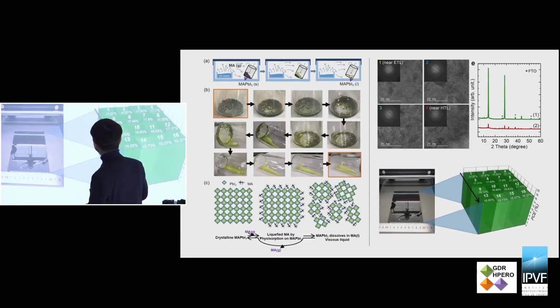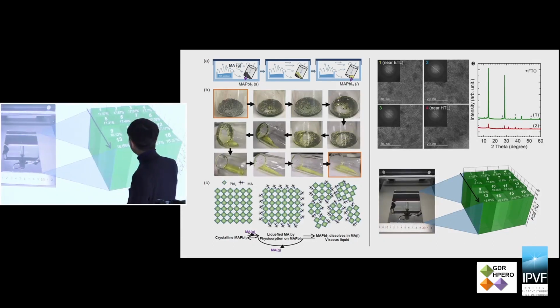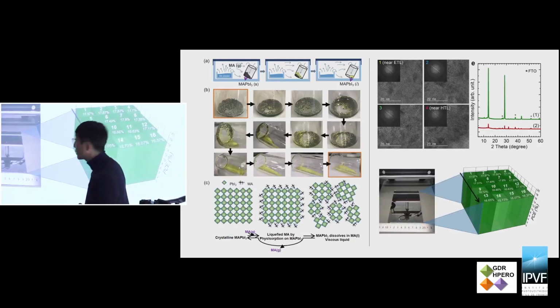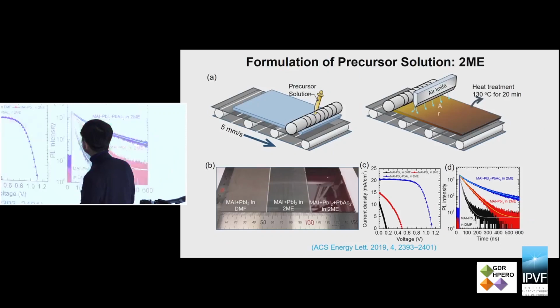And then we also found that this method produced a highly oriented perovskite film, from the TEM and X-ray diffraction patterns. And from this experiment we can get over 17% average power conversion efficiency. And also the other technology for large area coating, you can